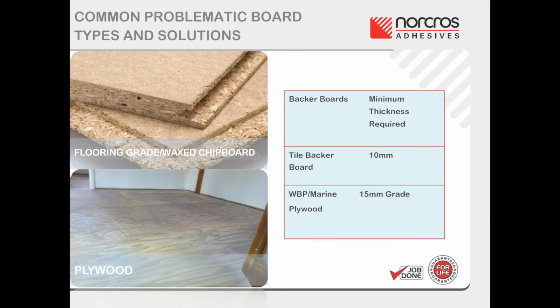Some existing floors may require strengthening, for example with an overlay of Class 3 exterior grade WBP plywood to BS EN 313 Part 2 or marine grade plywood to BS 1088. BS 5385 Part 3 recommends the required rigidity might be achieved by fixing WBP exterior grade plywood of 15 mm minimum thickness over existing boards and screwed to joists in existing boards at 300 mm intervals.